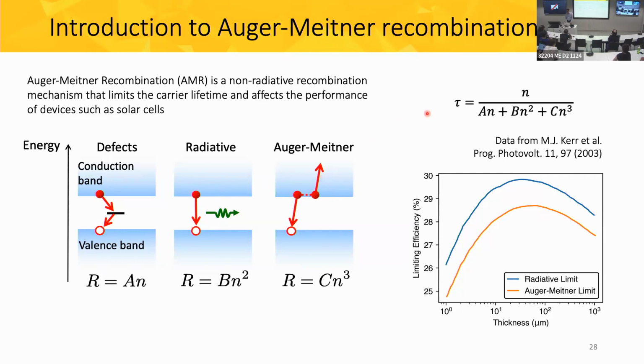The reason it's important is because it limits the lifetime of the carriers. When you produce an electron in a p-type solar cell, it has to cross the p-type region without recombining with holes. But holes act as traps, they can recombine. So that limits the lifetime. And as a result, it limits the maximum possible efficiency that can be obtained from a solar cell. So that's happening. It's real.